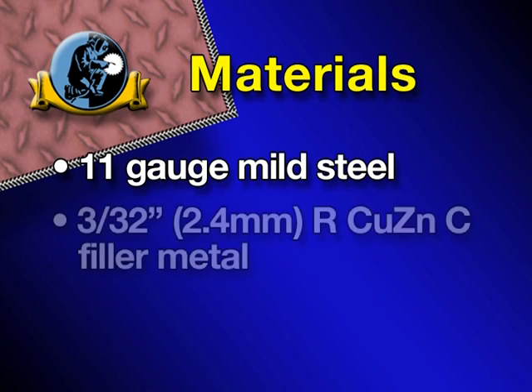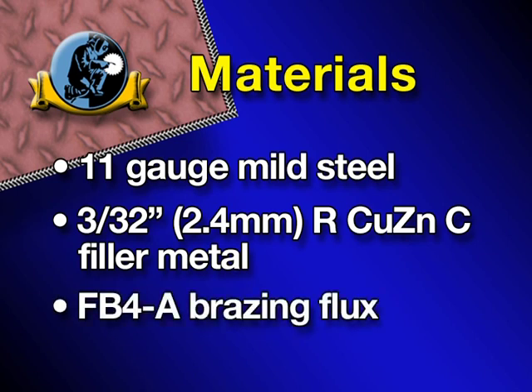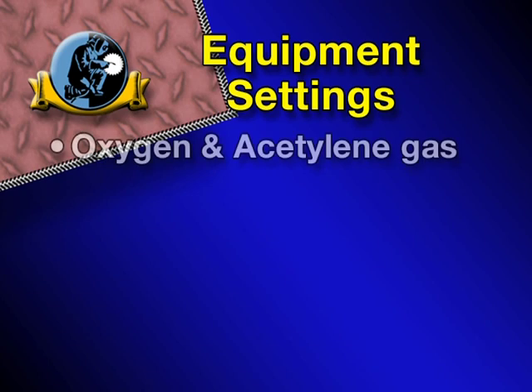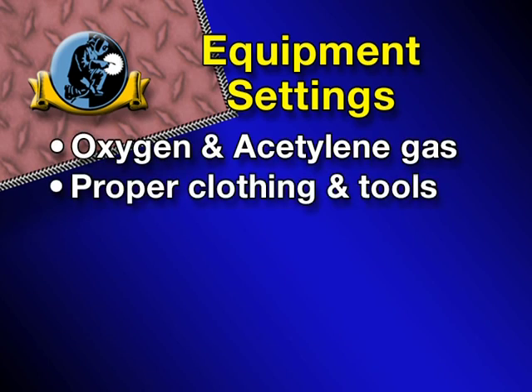You'll need some 11 gauge mild steel and some 3/32 inch type R CUZN-C copper zinc filler rods. You'll also need some FB4-A brazing flux. 3/32 inch pre-fluxed filler rods may be substituted for the R CUZN-C filler metal and flux if available. You'll need oxygen and acetylene gas supplies and equipment. You will also need protective clothing, gloves, goggles, a striker for lighting the torch, and a pair of pliers.